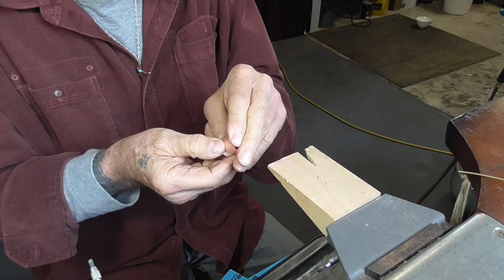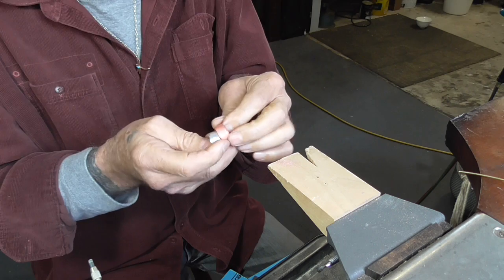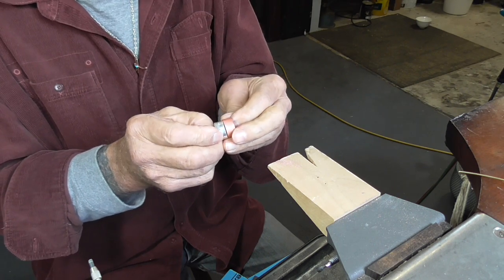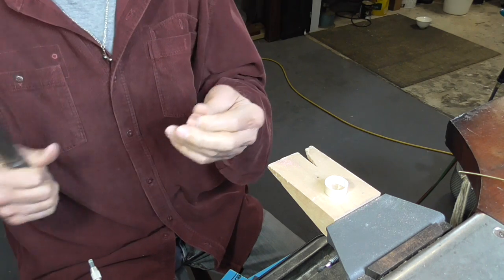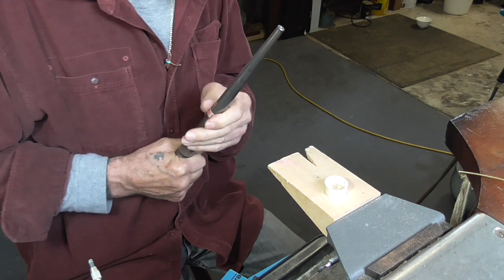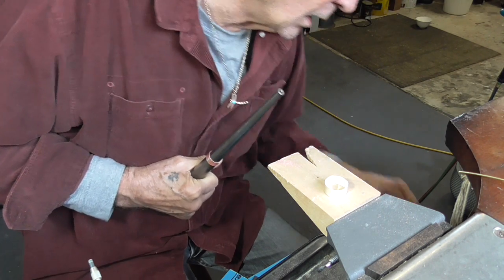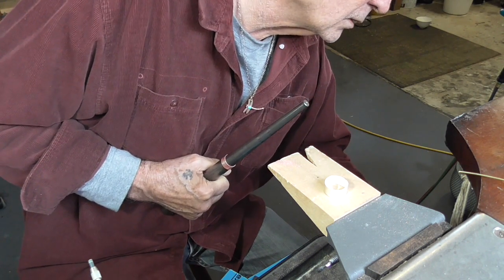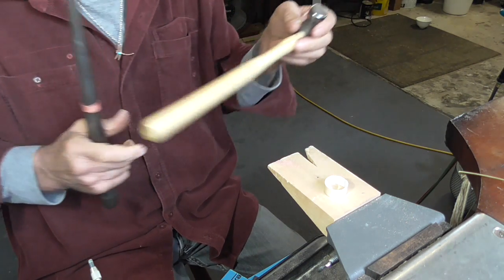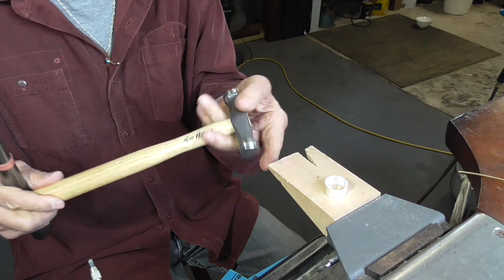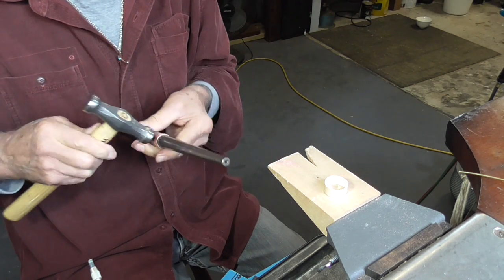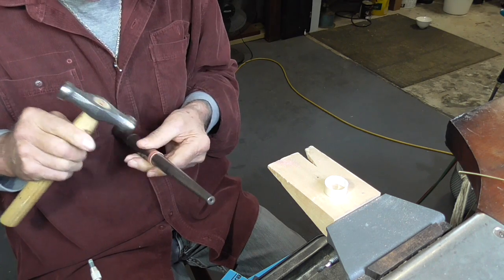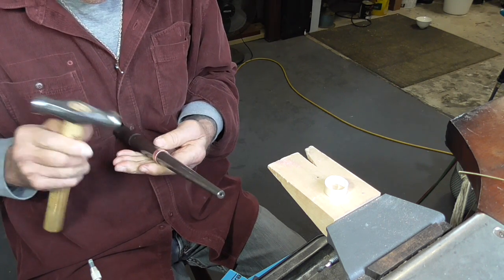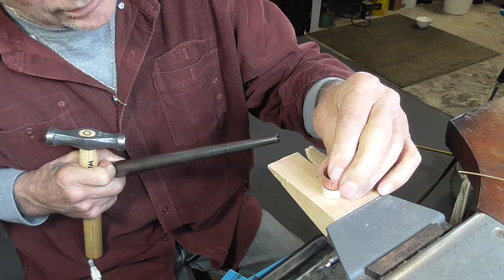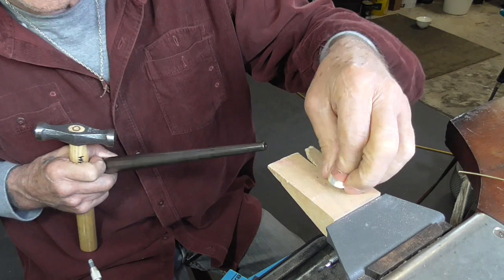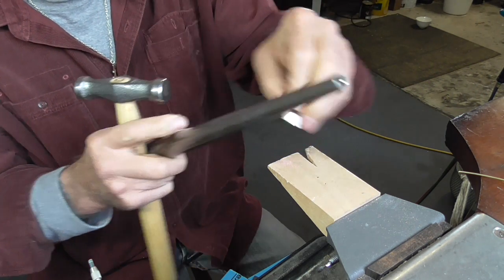So this should be a nice snug fit over the first ring. It's slightly small, which is what you want because it's always easier to hammer up a ring to stretch it a bit. And I'm using a planishing hammer and the flat side of the planishing hammer, not the domed side. So just the flat side, and don't kill it, but check it fairly often, because if you make it too big, you'll have to cut it and re-solder it.